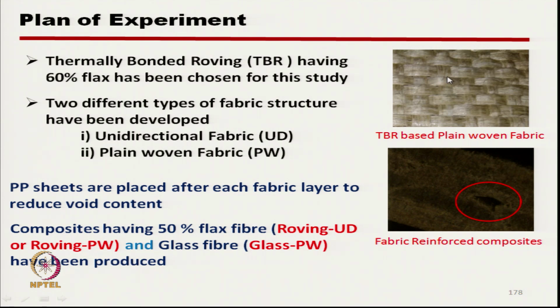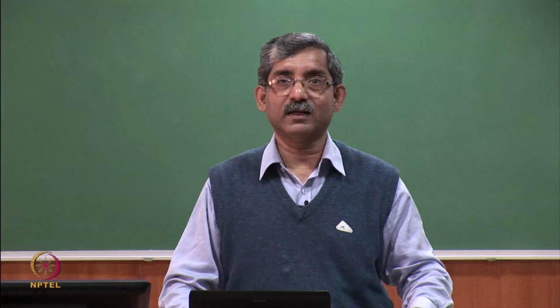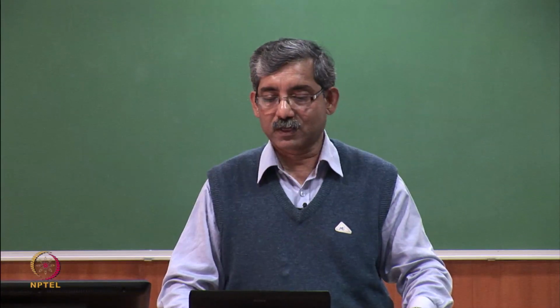Ultimately, in the composite it has become 50-50. Two different types of fabrics were used, unidirectional fabric, which we are calling UD, and plain woven fabric, PW. Once the composite is manufactured by the film stacking technique, this is the surface.